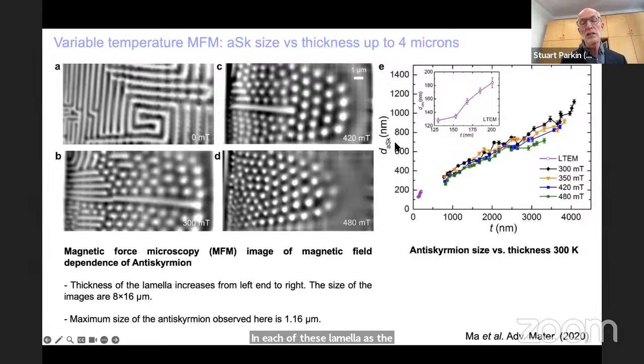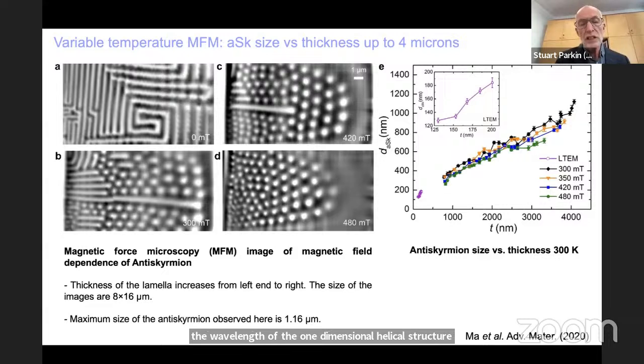And on the right-hand side, we plotted the diameter of the antiskyrmion as a function of the lamellar thickness at room temperature. And again, you can see a factor of 10 change in the diameter. And in fact, the diameter of the skyrmions is the same as the wavelength of the one-dimensional helical structure. So the reason for this dramatic variation in thickness we showed was due to the influence of dipole-dipole fields, which are more important the thinner the lamella is, and it actually causes a shrinkage of the size from that expected from the strength of the DMI and the Heisenberg exchange.